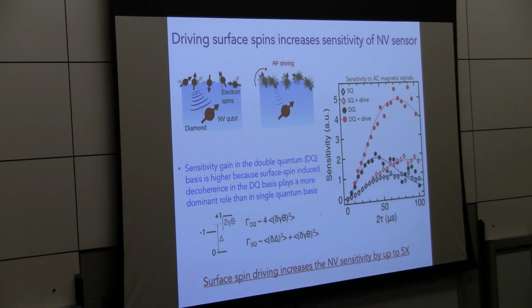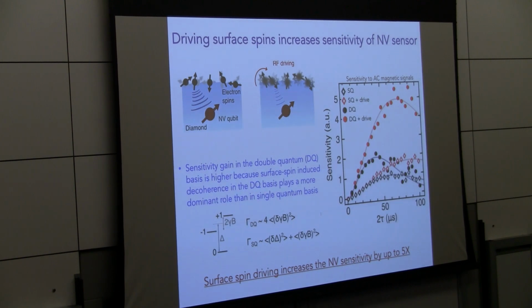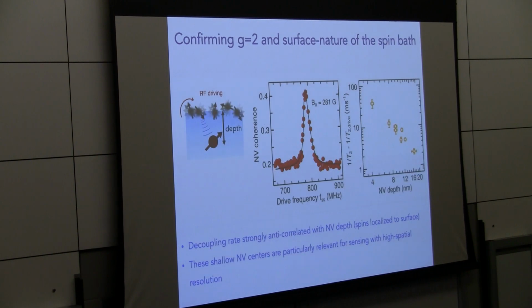As I mentioned, this is a fairly exciting direction, both in terms of a way to mitigate decoherence, but also these surface spins on their own are a very intriguing direction to go. This just shows that we can confirm that they really are at the surface if we measure the decoupled decoherence rate as a function of NV depth. We see that when the NVs get closer, we can decouple more and more of the noise, indicating that they really are at the surface.